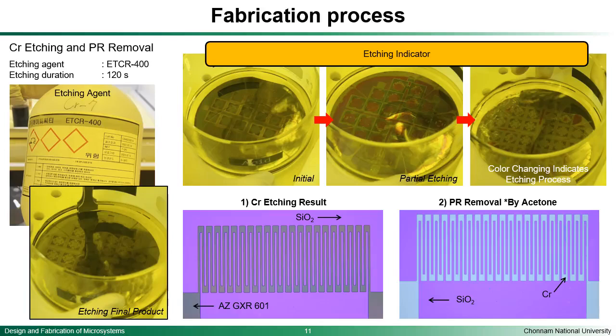Here we can see the comparison optical image of the chromium etching result. As I mentioned previously, the blue gray part is the deposited chromium, and right now the deposited chromium is already removed by the etchant. But the AZ GXR 601 PR still remains on the surface, so we use acetone to remove the covering PR. After removing it, we can see the blue gray part is the deposited chromium, and the purple part is the silicon dioxide. So the patterns of the sensor are very good.